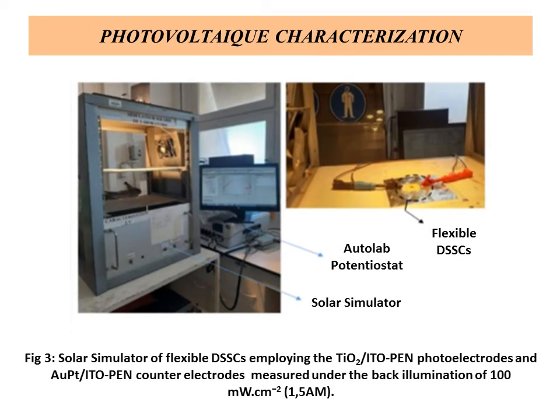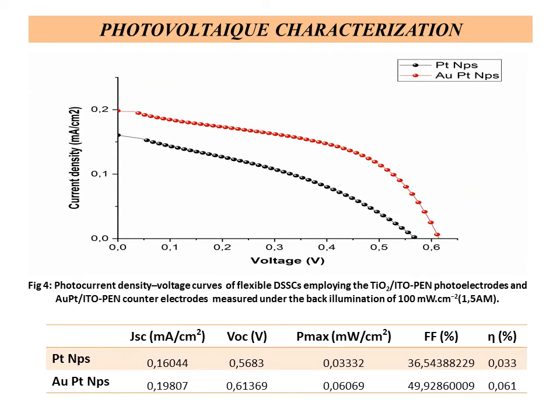Photovoltaic behaviors of the flexible dye-sensitized solar cell employing titanium oxide photoanodes and gold-platinum counter electrodes were measured using a solar simulator under the peak illumination of 100 mW per square centimeter. For the cell employing the platinized electrode, an energy conversion efficiency of 0.033% was obtained. However, the energy conversion efficiency of the cell increased to 0.061% by using the gold and platinum electrode.